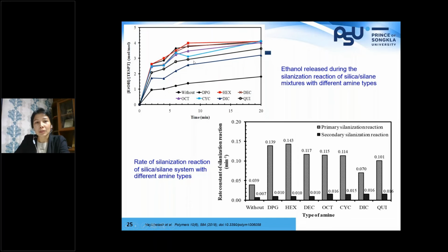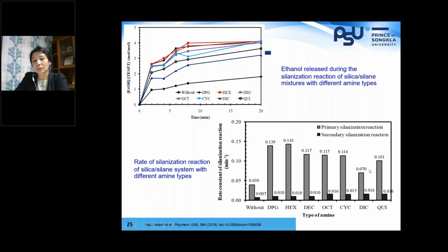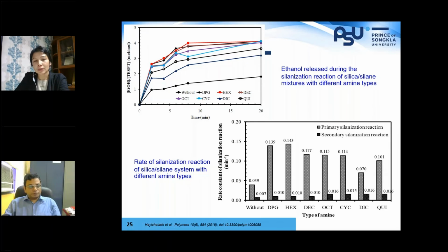By having amine, we have different concentrations of ethanol generated from the reaction. And applying those relationships, we have a rate constant here. So we have a much higher primary silanization reaction rate compared with the one without amine. And among those different types of amine, the different structure of amine has a different effect on the rate.